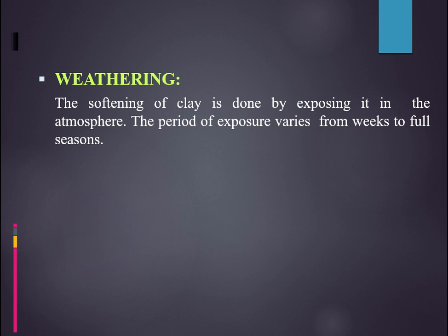Why? Because this weathering concept will help to develop homogeneity in the entire soil, particularly if it is from different sources. Means whatever clay you obtain for making brick is from different sources, and also to eliminate impurities which get oxidized sometimes. So that's the reason we allow the clay to get weathered. Okay, and even soluble salts in the clay can also be eroded by rain up to some extent, which otherwise will cause scumming at the time of burning of the bricks in the kiln.